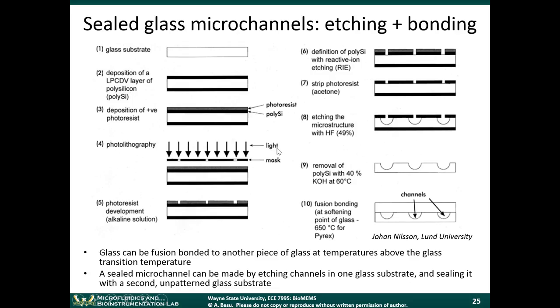Here's a slightly more complicated process. You start with a glass substrate, then deposit an LPCVD layer of polysilicon. Then deposit photoresist, expose it, and develop it to get a patterned polysilicon layer with small holes. First you deposit the polysilicon, deposit photoresist, expose the photoresist, develop the photoresist, then use RIE to transfer the photoresist pattern into the polysilicon layer underneath, and then remove the photoresist — all that just to get a patterned layer of polysilicon.